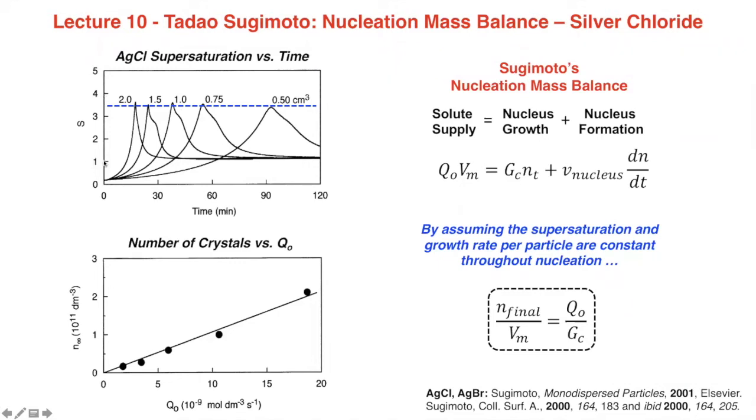Equilibrium, when you divide the actual by the equilibrium, you're at 1. So this is the equilibrium concentration. These reactions get to supersaturation ratios of about 3.5 or so. So once you hit that level, nucleation turns on in very dramatic fashion, as proposed by the classical nucleation picture.